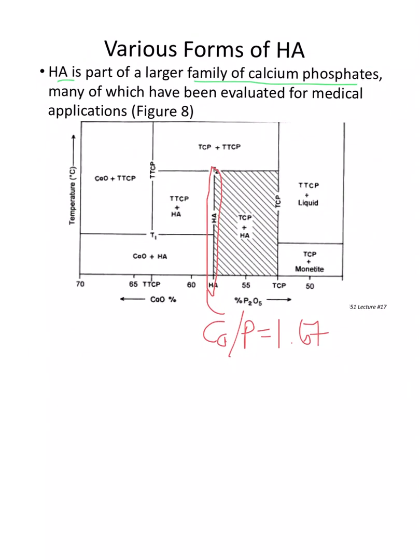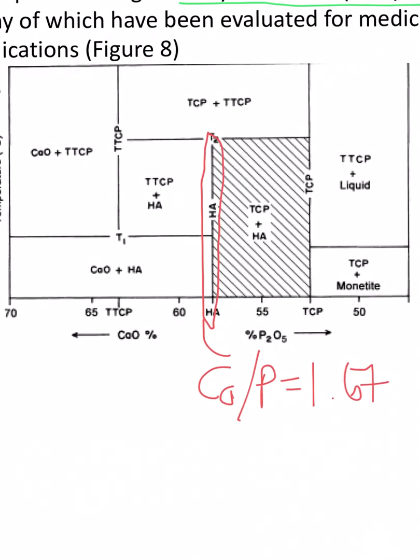All right. And so pure hydroxyapatite only occurs at one specific point on the phase diagram. Everything else is not the same. And that's significant because it means that you need to have precise control if you want pure hydroxyapatite. Now, the thing to note here is what happens if it's not pure. If you go in the direction of too much calcium, you're getting calcium oxide. If you go in the direction of too much phosphorus, you're getting this tricalcium phosphate.